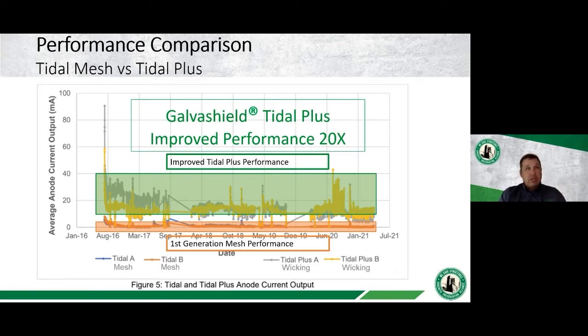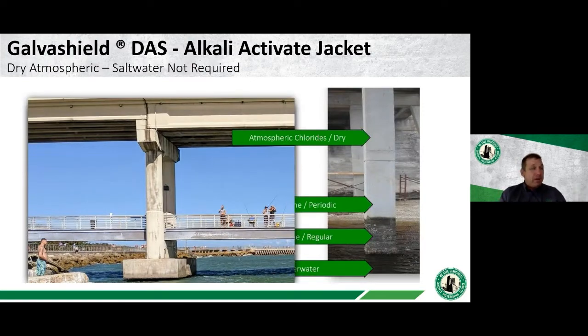So that's just another update in terms of improvements to the Tidal jacket that has been done in the most recent years. So then what do we do when we start to move up into the atmospheric area or that dry zone? When we start to move up there, there's a limitation even with the wicking anode or the Tidal Plus anode. As we start to move higher and higher, that capillary action can only go so high. So what happens when we get outside of that zone and we're in that atmospheric area or dry zone where we have the airborne chlorides?